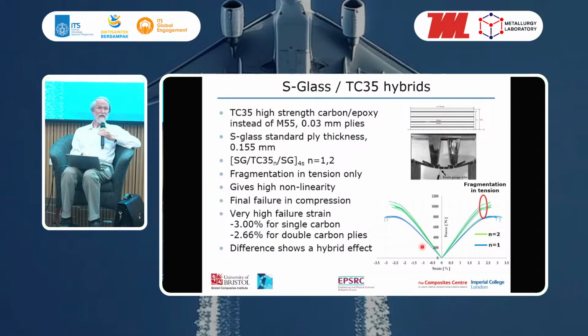No fragmentation in compression, because this fibre has got a much higher compressive failure strain than the M55. In fact, the compressive strain to failure is higher in compression than it is in tension. And so what we see is a similar behavior in tension with fragmentation, and then it goes beyond that knee point strain, and then we get final failure. So what's interesting here is that the 2-ply case is stiffer, as you'd expect, with 2 plies of carbon, stiffer than with 1 ply of carbon.